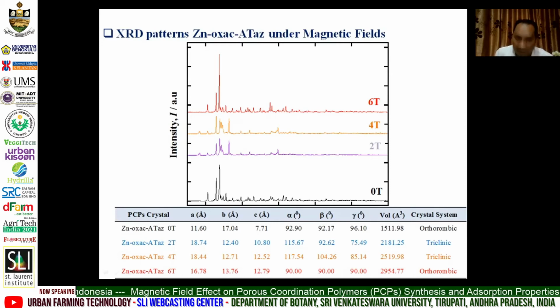Even the highest intensity is for 6 Tesla, higher than 0 Tesla. The difference of this second PCP, compared with ATaz: if ATaz changed from monoclinic to triclinic, this PCP at 0 Tesla and 6 Tesla forms the same crystal system, orthorhombic, but the 2 Tesla and 4 Tesla, with significant change of the intensity of the XRD pattern, change to a triclinic system.